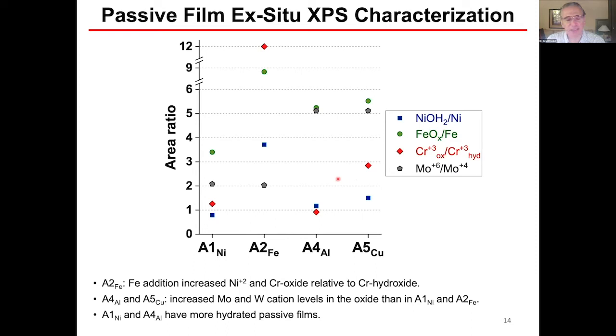Further analysis suggests, and we've done a lot of different analysis, one thing that comes out of this is that the nickel and the aluminum alloys are more hydrated. You can see the low value of oxidized oxide as opposed to hydroxide related chromium 3+ is lower here. So these two alloys are more hydrated compared to the one in particular with iron or with copper. And when we add iron, in fact, it's increasing the nickel concentration as well as the iron concentration in the alloy, which is quite interesting.